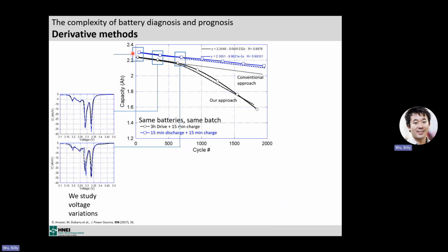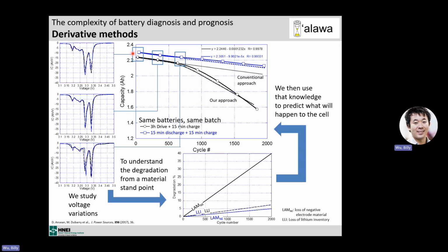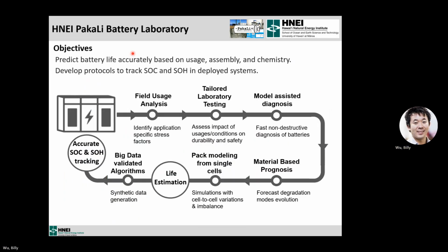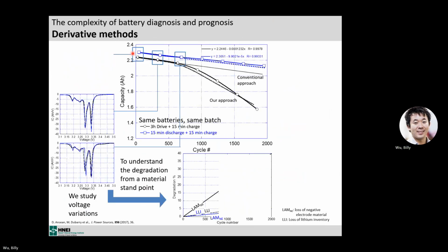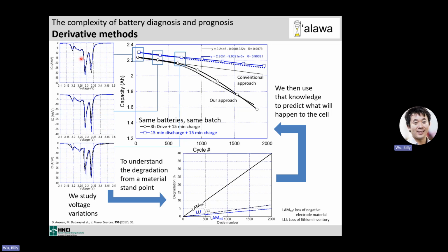And we knew that, oh, sorry, the animation is screwed up. We knew that because when we looked at, not used to that clicker, when we look at the derivative, we could see that the changes were not the same. And we could see that for the black one, we were losing negative electrode 8 times faster than the blue one, and it was irreversible. And so when we extended those trends, we predicted that the capacity was going to dive. And we could have done it as early as cycle 250. We knew that bad cell was in trouble.